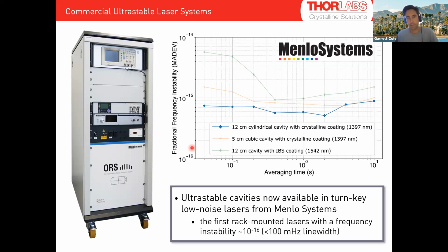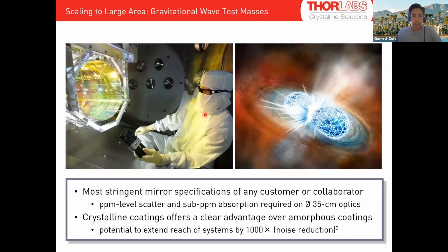Right? These things are very still, very quiet cavities in a rack, which is quite impressive. So you're having an active vibration isolation platform, good temperature control, and so on. And it's really our crystalline coatings that can push these ultimate limits of stability over a fairly wide frequency range there. An exciting R&D area that we push into is expanding or scaling up the diameter of these coatings to do large area optics for LIGO.